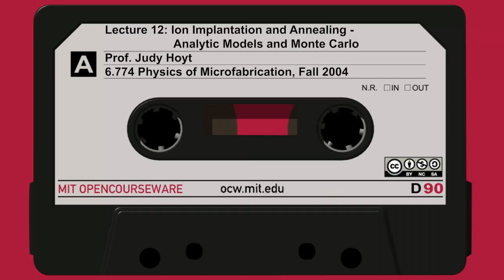The ion source extracts the ions at a given energy, say from 0 to 30 keV. We can set the energy of the ions coming out just by knowing this extraction voltage, V extraction, that we apply to this grid. So we know the energy of the ions coming out, and then we do what's called an E cross B filter. This happens in any kind of mass analyzer. This is what's happening when you do secondary ion mass spectrometry. If you know the energy of the particles coming out and you bend them in a magnet, you can mass analyze them and only pick those ions that have the right mass.